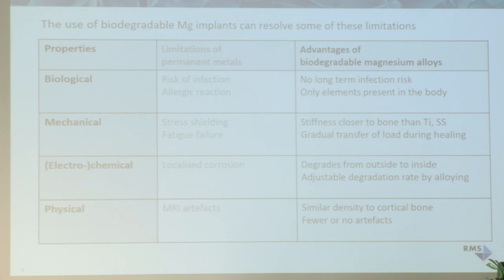On the chemical side, with the new generation of alloys, we have a completely uniform degradation from outside to inside, not like polylactide where you have bulk degradation. And by alloying, you can also, within certain limits, adjust the degradation rate. When it comes to MRI, magnesium has a similar density to cortical bone, and we have seen nearly no artifacts. So this is not a problem for magnesium.